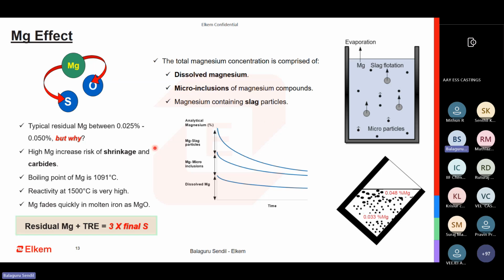But the magnesium you measure here is a combination of three things. We have dissolved, micro, and slag. The slag is of no use. It is quite big and it keeps floating out. You can see the image here. If you take a ladle and take the sample from the top, it is always going to give you high magnesium, but what is actually inside is different.